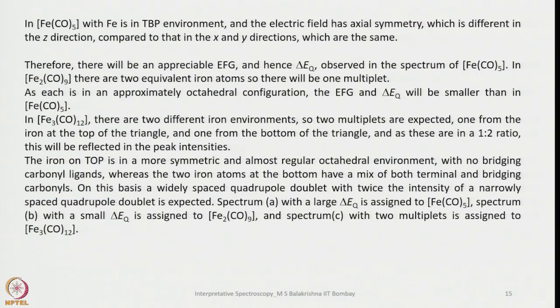So that means in the case of FeCO5, iron is in a trigonal bipyramidal geometry, with three carbonyls in the plane and two in the axial positions, and the electric field has axial symmetry, which is different in the Z direction compared to the X as well as Y directions, which are essentially the same. Therefore, there will be an appreciable electric field gradient, and hence delta EQ is observed in the spectrum of FeCO5.